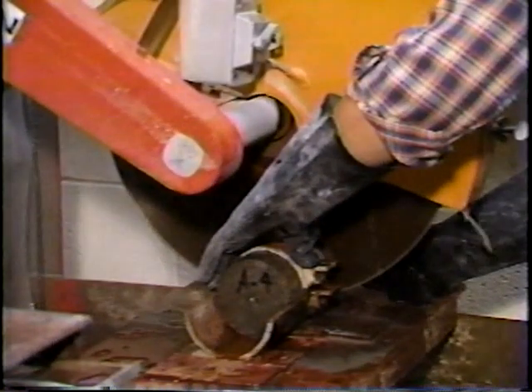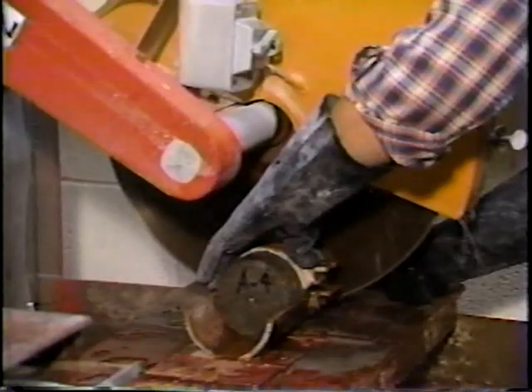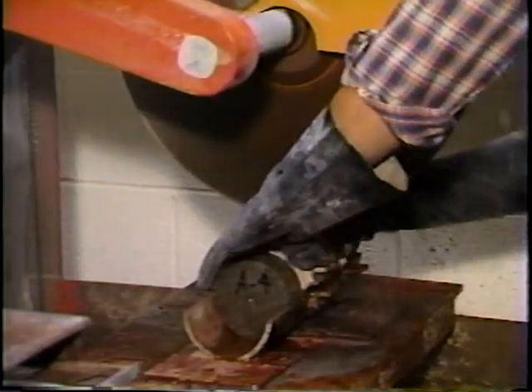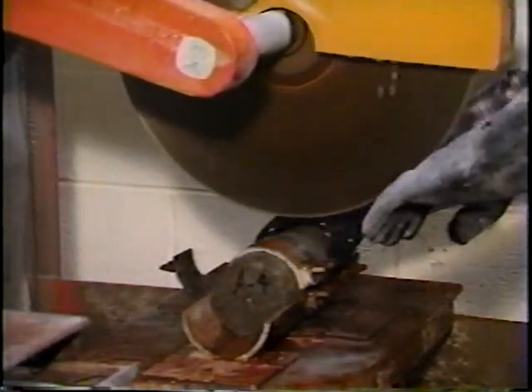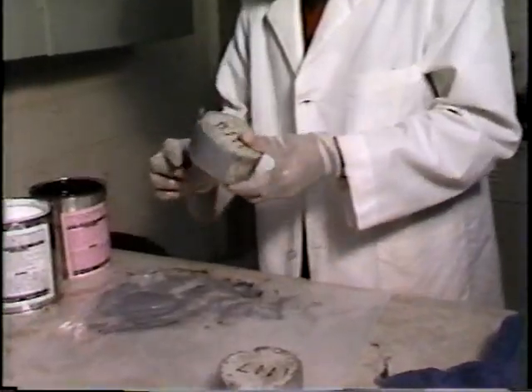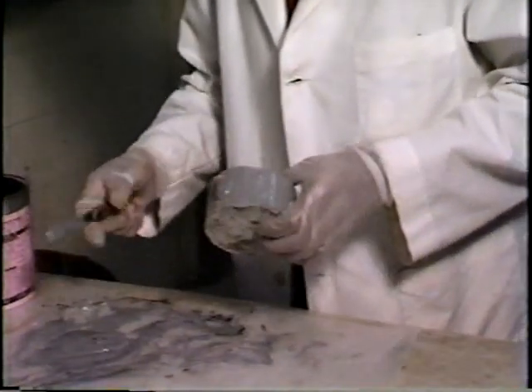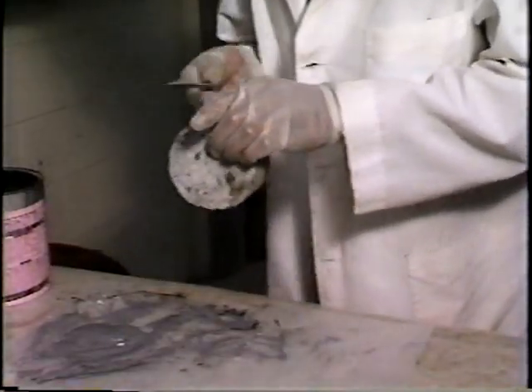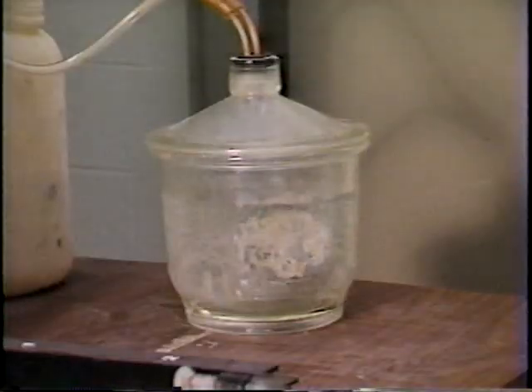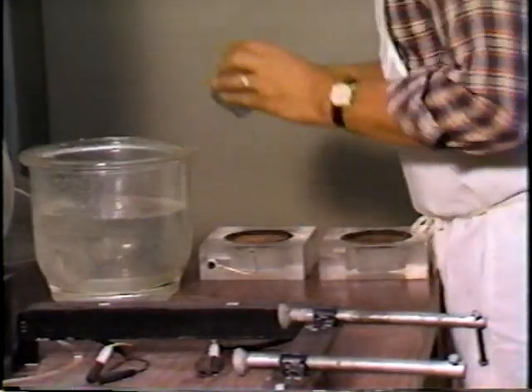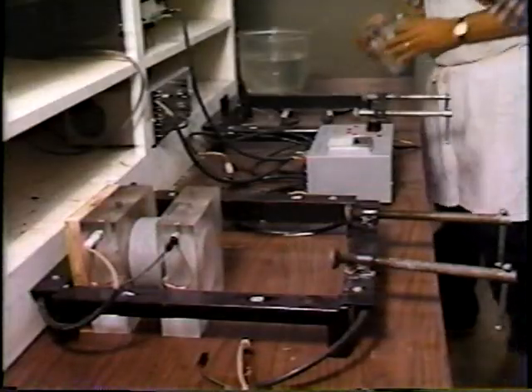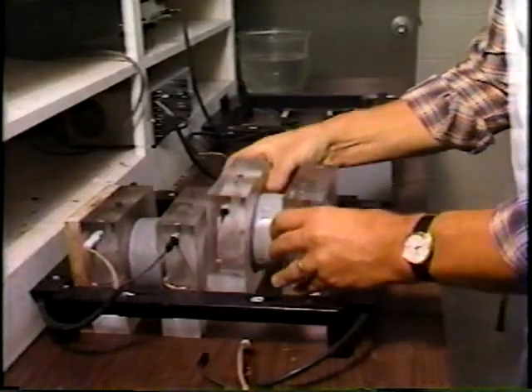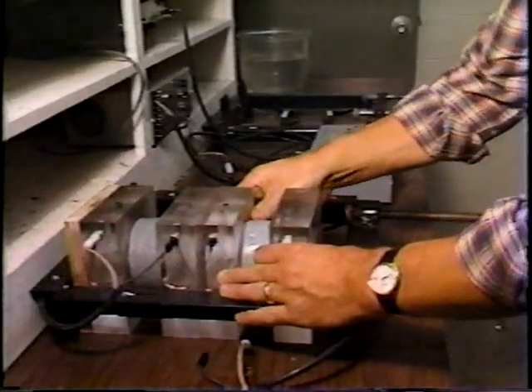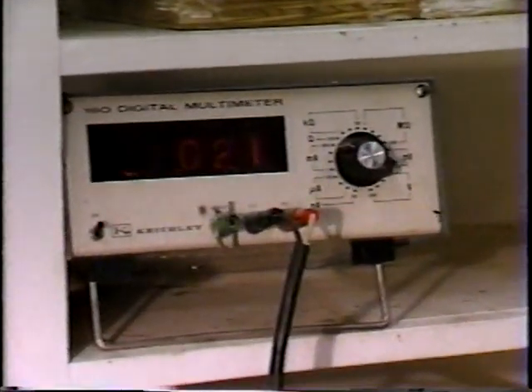When permeability is to be determined, a 2-inch thick section of a core is cut on this water-cooled diamond saw. These sections will be epoxied on the outside edge to make this edge impermeable. Then they are vacuum saturated with water and tested in this apparatus, which electronically measures the speed at which chloride ions penetrate the specimen. Chloride ions placed in one cell have to get through the concrete to the other cell to make the meter work.